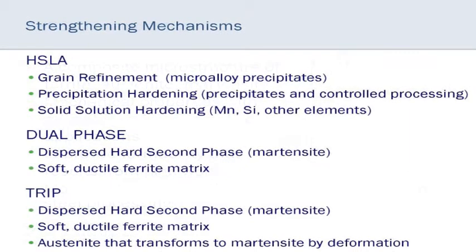So high-strength low alloys were produced by grain refinement, precipitation hardening, and solid solution hardening. Dual phase is a dispersion of a second phase, a very hard phase, within a soft ductile ferrite matrix, so the ferrite can be formable, but when you form it, then that strong martensitic microstructure helps give you the strength.